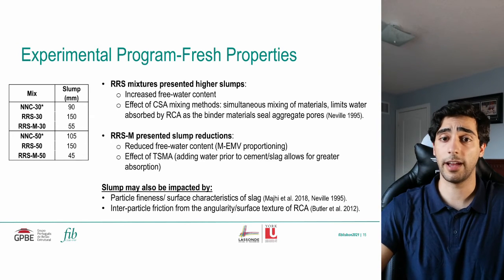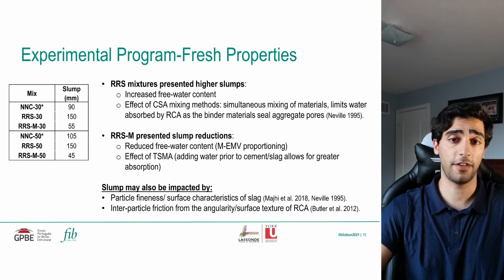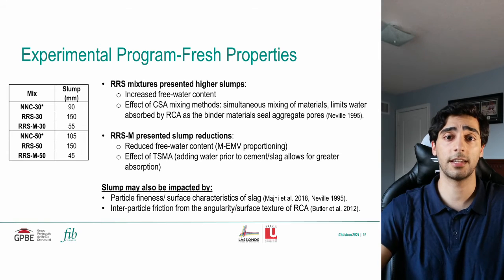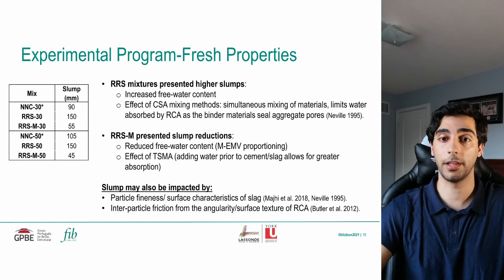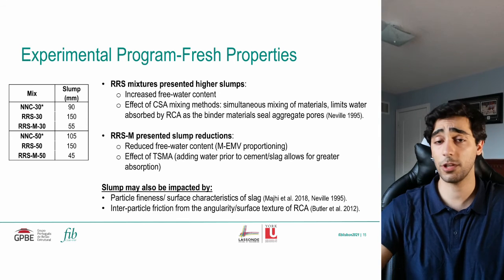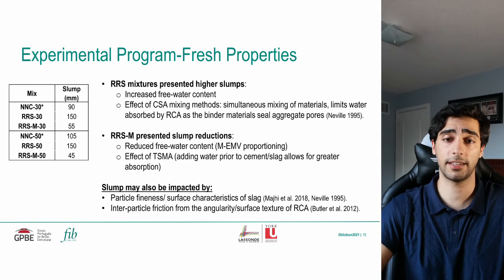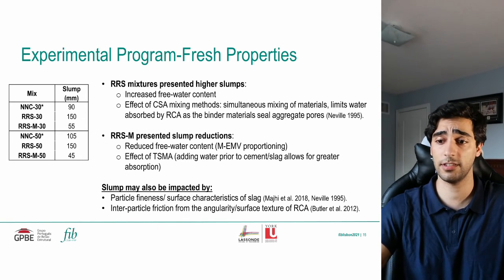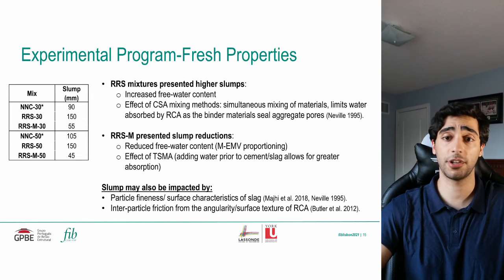While in the RRS-M mixtures, the reduced free water content of the modified EMV-based mixture proportioning and the effect of the two-stage mixing approach, consisting of the separation of the water and the cement content, allow for further absorption, reducing the free water content and workability of the mixtures. It should also be noted that the slump values were also impacted by the particle fineness of the slag sources, as well as the interparticle friction and increased angularity of the RCA sources.